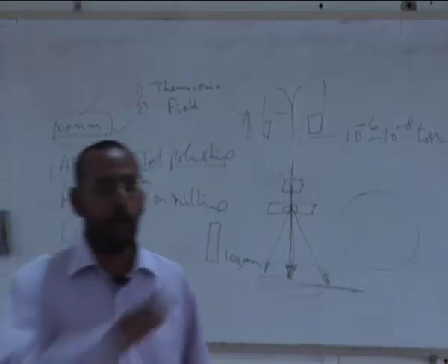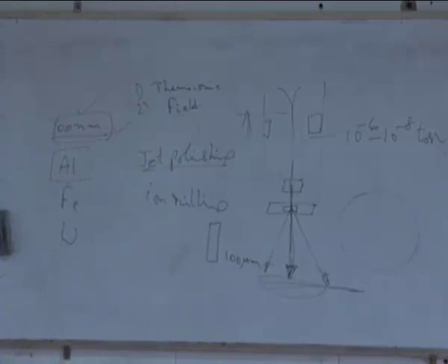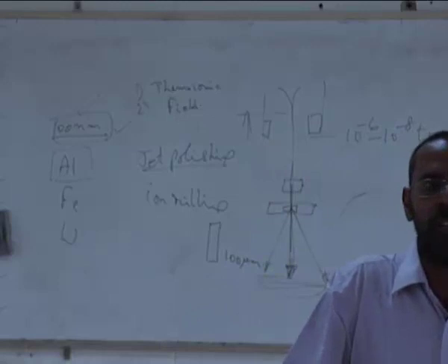The only way to make a ceramic material into such thin is if you can somehow polish a ceramic material without breaking it. So that's why handling ceramic materials is not very easy in a TEM. So there are special techniques available, particularly certain diamond tools, where even a brittle material can be cut into very thin slices.